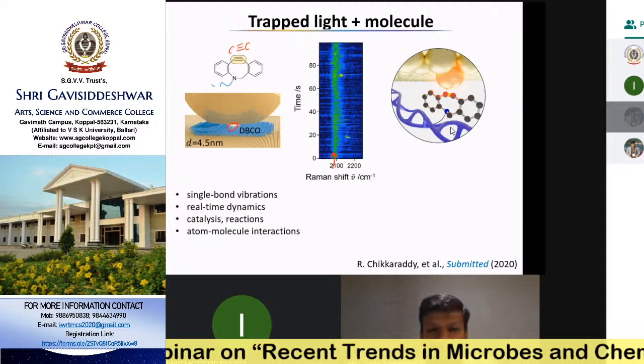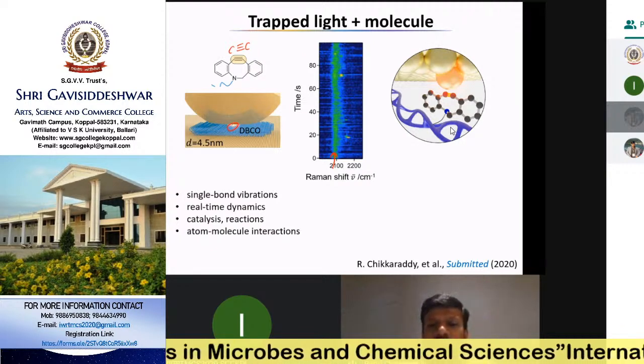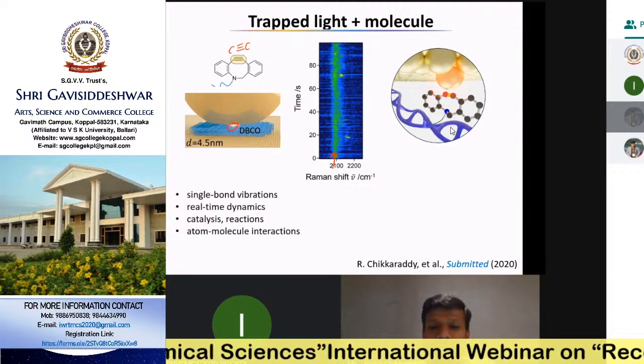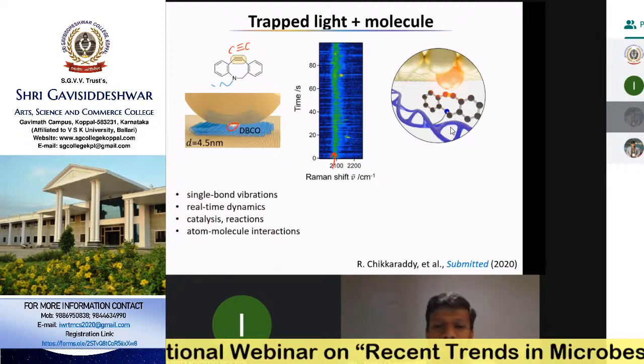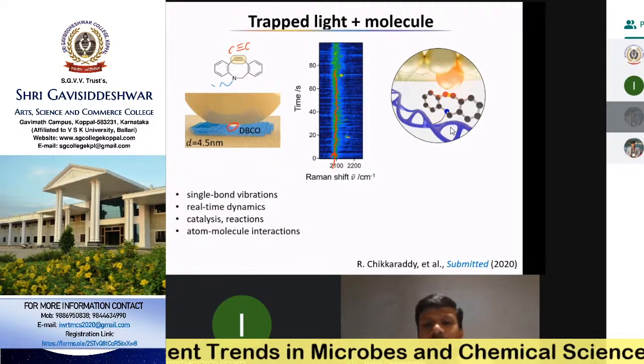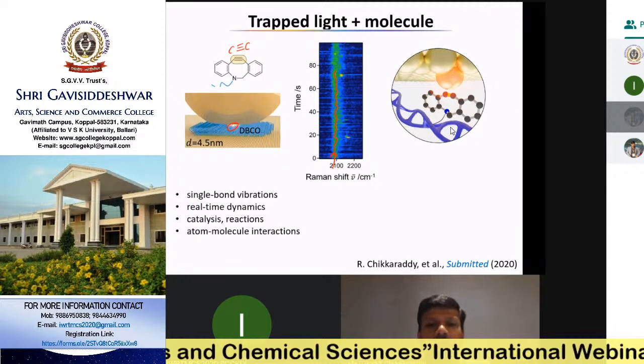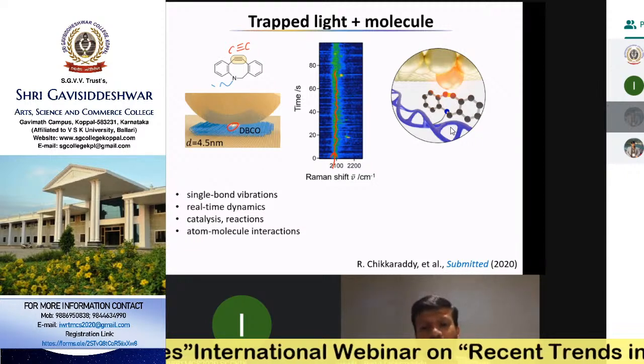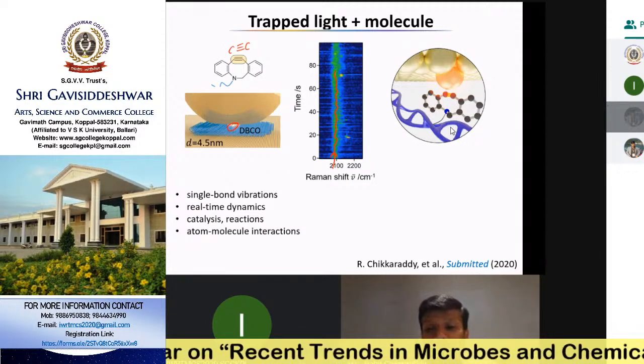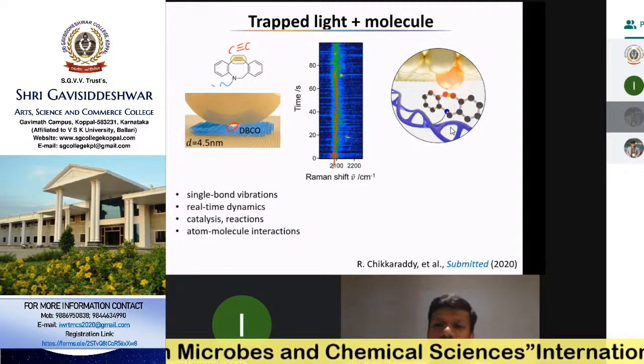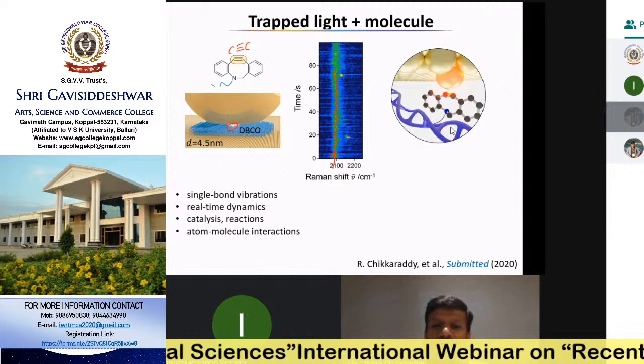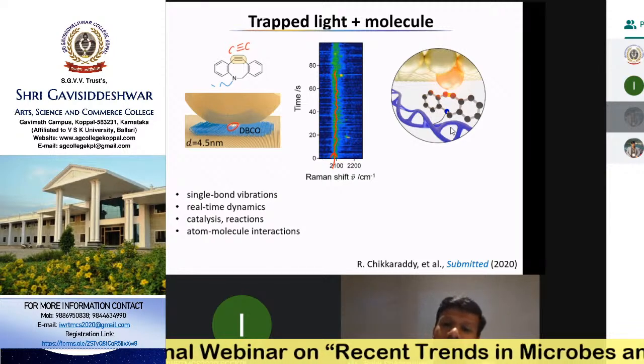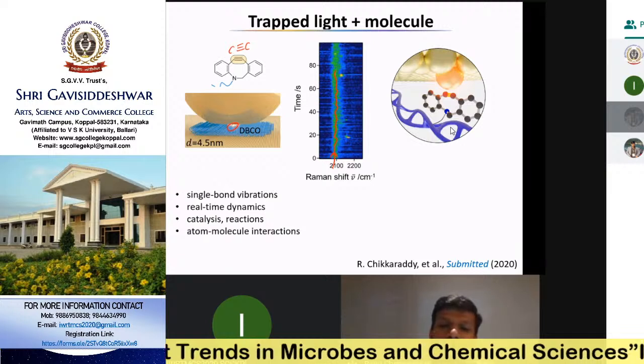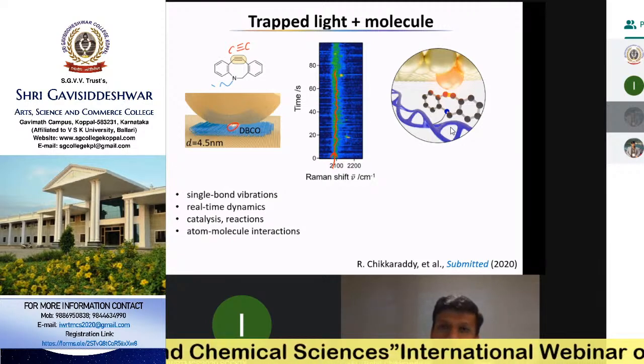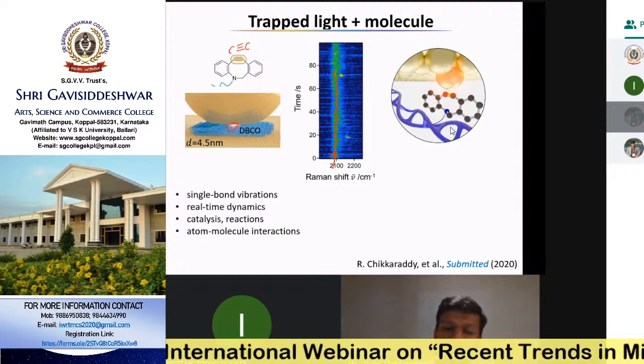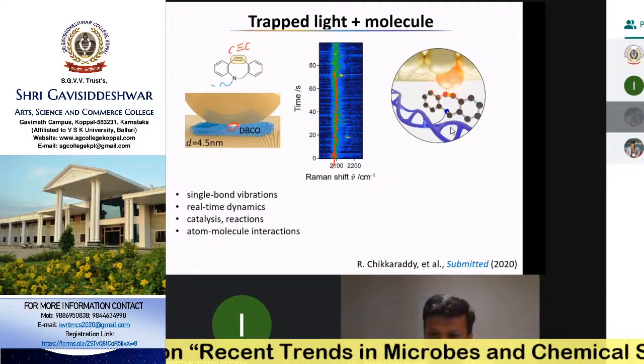And like all textbooks say, you have one bond, you have one vibrational energy, and that vibrational energy won't change. But in fact, in experiment, what you see is the vibrational energy changing over a period of time. And it's very hard to understand why a bond vibration would change. Carbon is carbon, it's an sp hybridized bond, so there should be no change in the vibration. But it turns out any small local change as the molecule bends, flexes, and twists, this bond energy slightly changes. And this slight change in the bond energies is at the heart of how catalysis works, or even at the heart of how protein binding works, or how functional groups understand their orientation